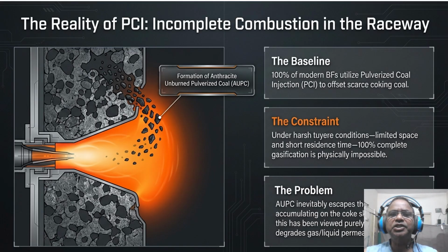Look at that injection point. You have got a massive volume of coal hitting a high velocity airstream in an extremely limited space. Under these conditions, limited space and incredibly short residence time, complete gasification is physically impossible. We are talking in the context of 12 to 15 milliseconds. So anthracite unburned pulverized coal, or AUPC, inevitably escapes the raceway and starts accumulating on the coke skeleton.